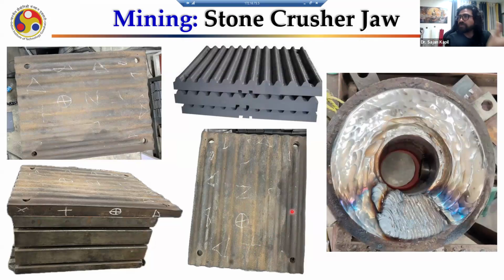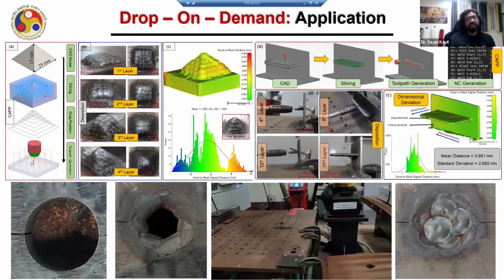So we provided them a lot of samples with different materials deposited, and they finalized the material that they wished to be deposited. 30 kg only, and this die will be back to life. We'll send it back by depositing a different material, not the main material. This is a stone crusher that actually got worn out. When I say repair, repair doesn't come with a known shape. It can get repaired from anywhere.